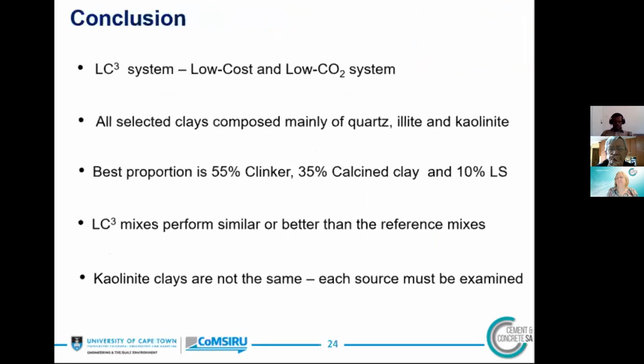So to conclude, LC3 system is a promising option for lowering cost and environmental impact of cement. All selected clays are composed mainly of quartz, illite, and kaolinite. From the optimization results, the best proportion is 55% clinker, 35% calcined clay, and 10% limestone. And from the results, it's clear that LC3 mixes perform similar or better than the reference mixes.